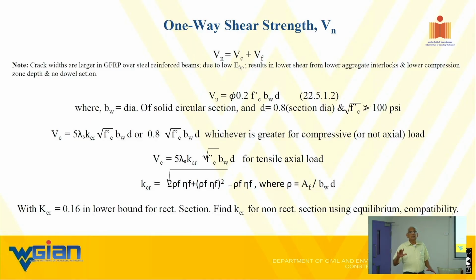The reason is the crack widths are much higher than those in steel-based, and you have to have certain lower ranges of crack width for interlocking effects to take place. But if on the other hand you mean that when I am doing this, I'm balancing the forces resisted by rebar, that's correct.